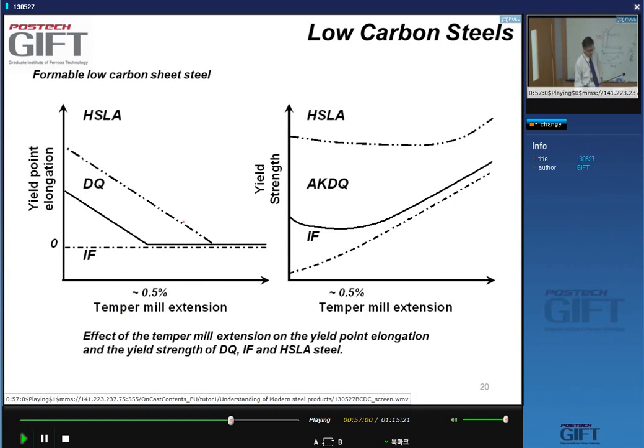Yes, the temper mill. Let's have a look at what the effect of the temper mill extension is on the yield strength when I increase it. In the case of aluminum-killed drawing quality steel, you go through a minimum in the yield strength and then an increase as a function of the temper mill extension. What happens if we have an IF steel?